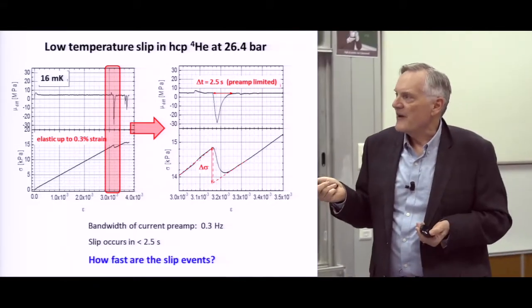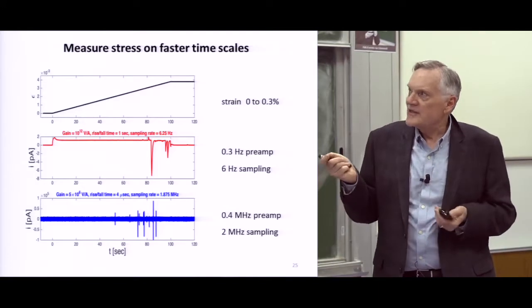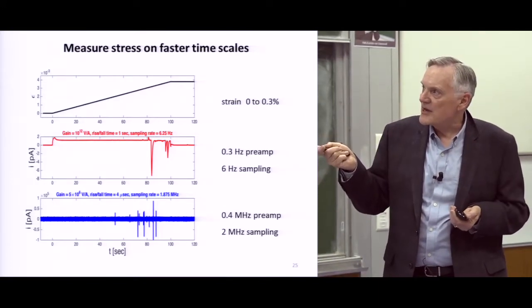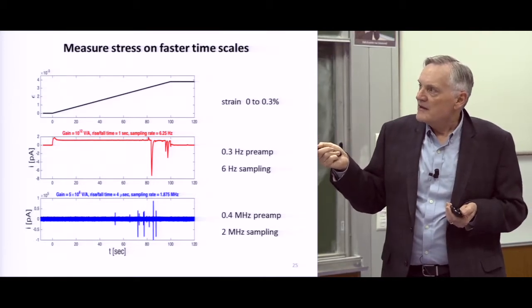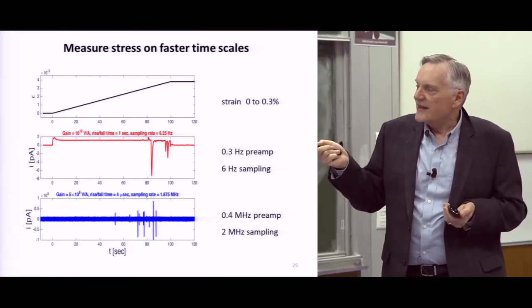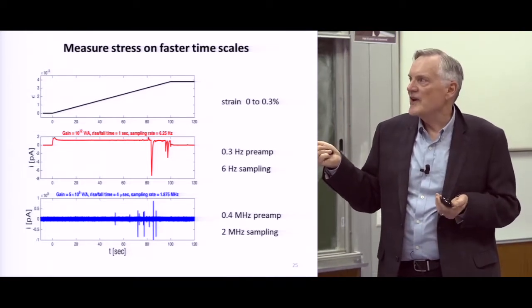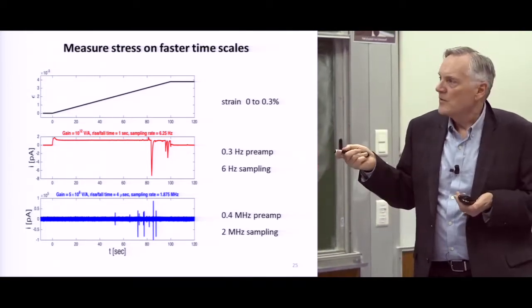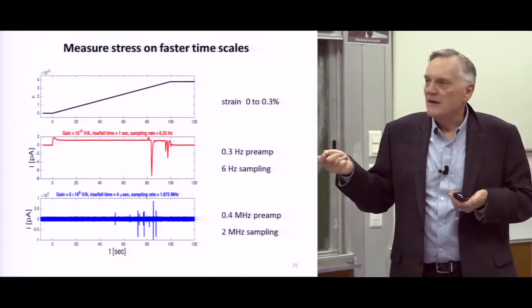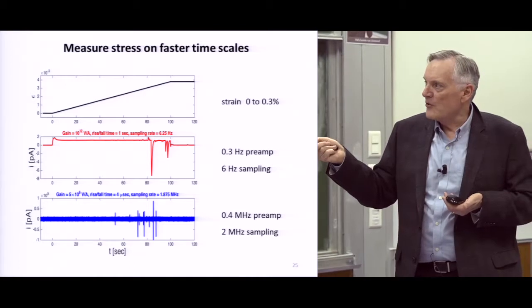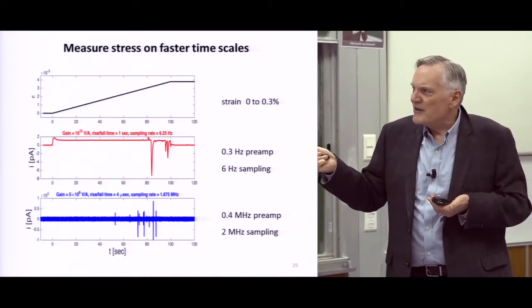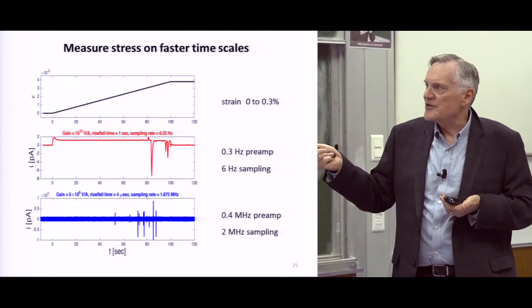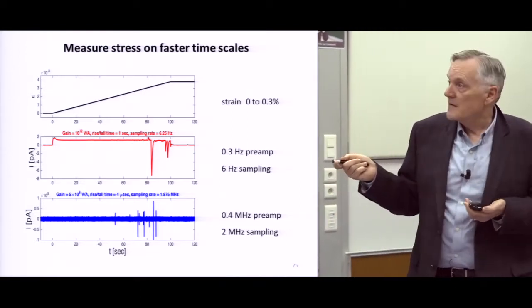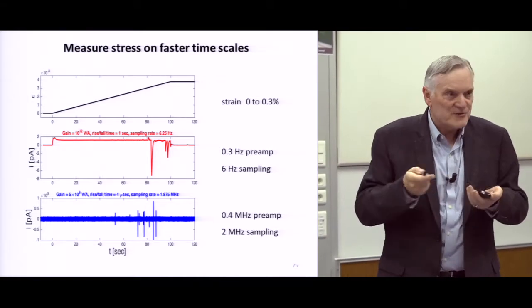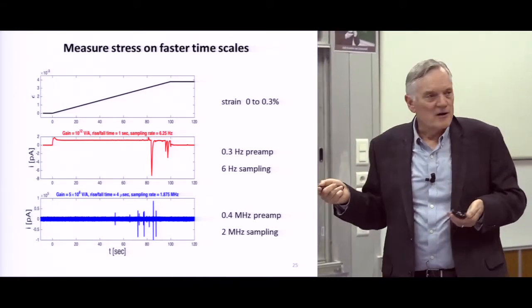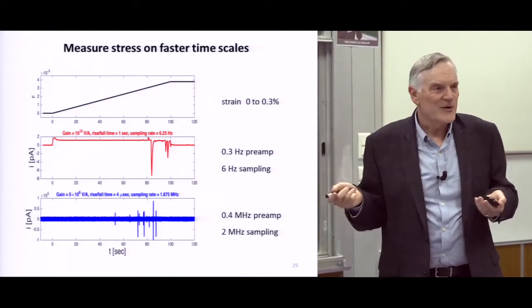So we, of course, want to do it faster. So we did the same experiment. The upper one is the measured strain ramp as a function of time. This is the data that I showed you before. These are the glitches. This is a 0.3 hertz preamp, sampling a few times a second, very slow. With the same crystal, different run, we did exactly the same thing. We deformed it over about 100 seconds. And we see things, but they seem much sharper. That's because we've now switched to a 400 kilohertz preamp, so we can measure things as short as a few microseconds. And we sampled at a couple megahertz so we could do this. So there's a lot of data in 120 seconds, actually.